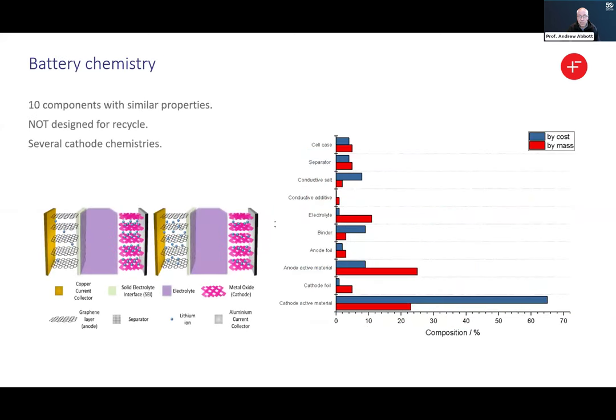So what everyone knows is that what we're trying to get to, or what everyone's focusing on at the moment, is the cathode active materials, because those have by far the largest value by composition. However, what we should do is to also focus on the other active materials and see how many of those we can get back in a pure form. And the real problem associated with this is that the components have very similar physical properties, and there are lots and lots of different components in there, which are usually very difficult to separate. And we've heard already about the complexity of PVDF, which is a nightmare to that recycling process.